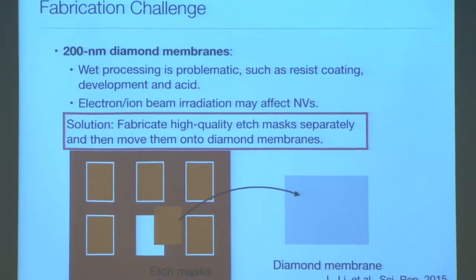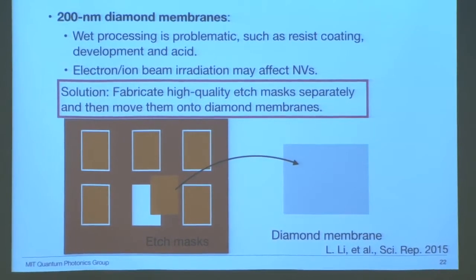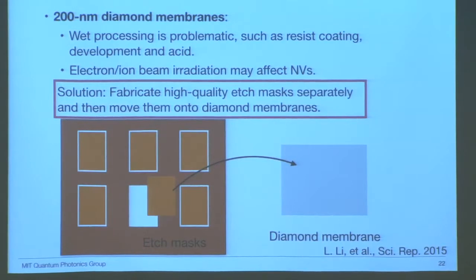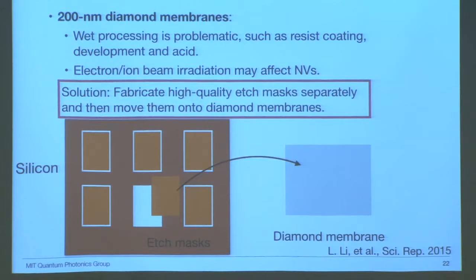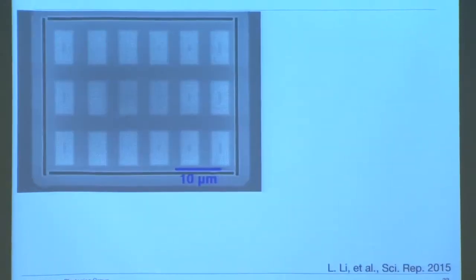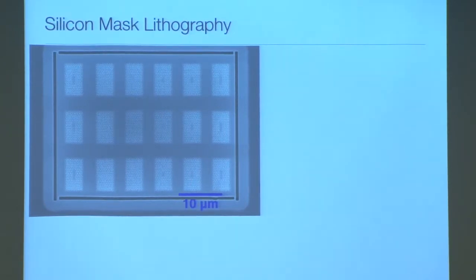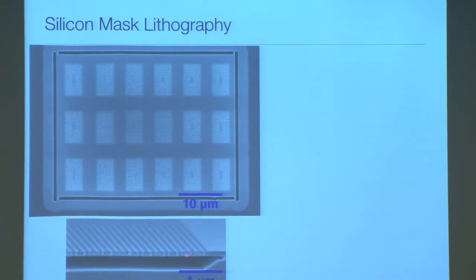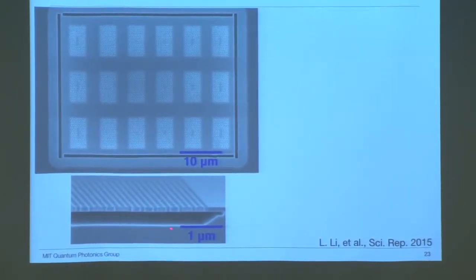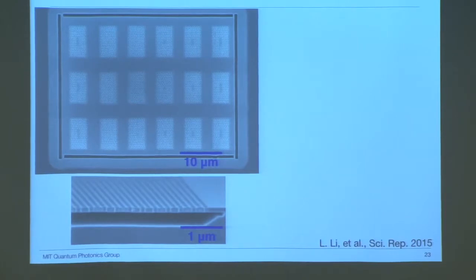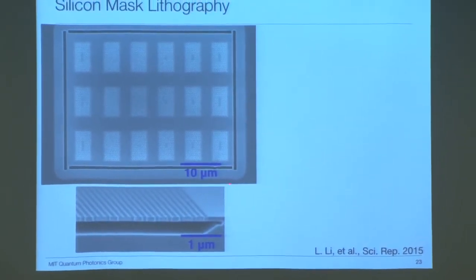Our solution is to fabricate high-quality etch masks on another substrate and then move them onto the diamond membrane. We tested a lot of materials. Silicon proved to be the best, as I will tell you why in the following three slides. Silicon masks can be produced from silicon-on-insulator wafers, as there exist mature fabrication technologies to make it happen. This is a side view of a silicon membrane on top of an oxide layer, and the oxide layer was removed by HF, and that's also why the color looks lighter than the bulk.